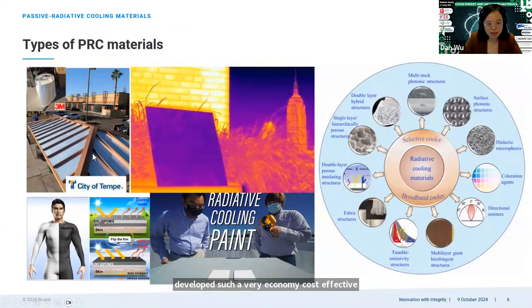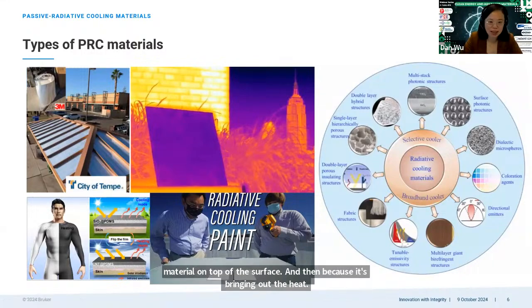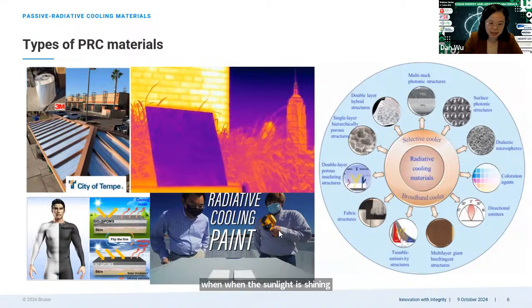And just imagine that you have this material on top of the surface, and because it's bringing out the heat when the sunlight is shining, if you are testing the temperature of this area, you will have the colder or lower temperature of the area where this passive radiative cooling material is covered. And without the covering of such material, you will have higher temperatures.